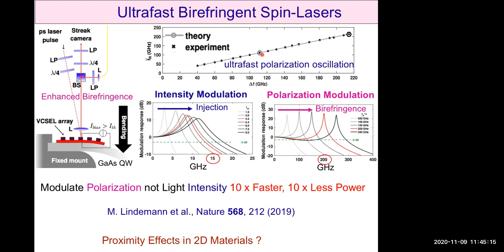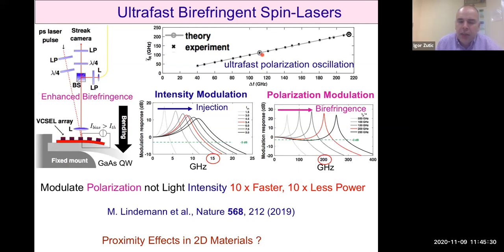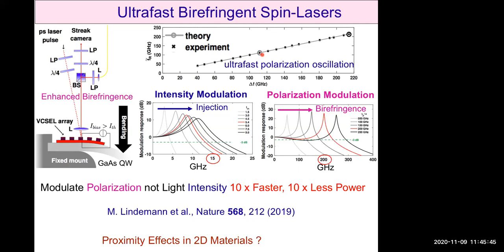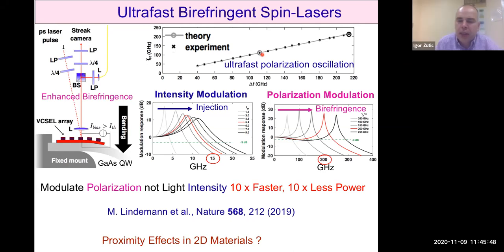Okay, so if I understood correctly, with this you're using just a constant pumping. So your spin population is basically constant. There are two things. This is basically a hybrid scheme. These lasers are relatively standard, using standard materials where carriers are added by electrical pumping. But we don't have efficient room temperature spin injection. So the spin that is needed is added by sending picosecond pulses of circularly polarized light.